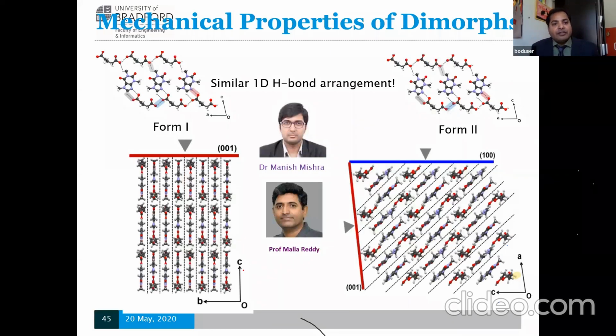So we continued also with this interesting system on the mechanical properties with caffeine glutaric acid, which is a dimorphic co-crystal, form 1 and form 2. The major work of this has been done by Manish Mishra. He is now currently working at the University of Minnesota, and Professor Malla Reddy has long-standing experience with the mechanical properties. If you look at the crystal structure of Form 1 caffeine glutaric acid, it has a nice layer structure formation, and in this 001 plane, you have very good slip planes, and